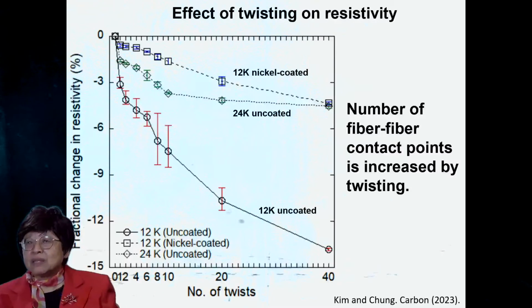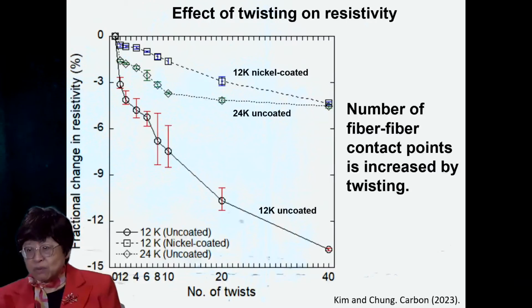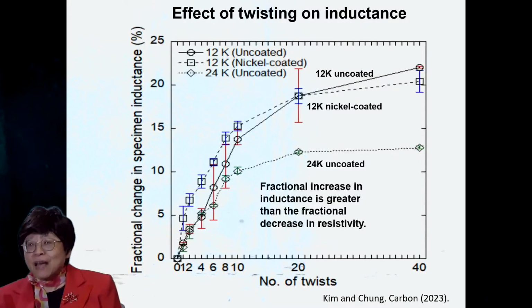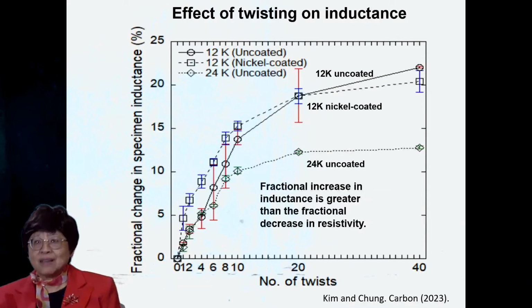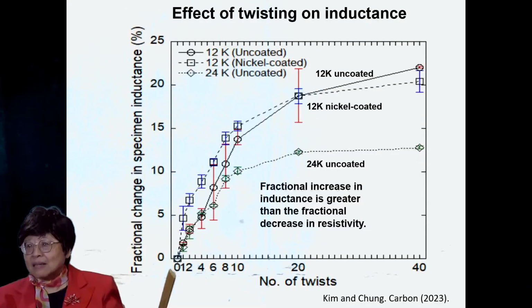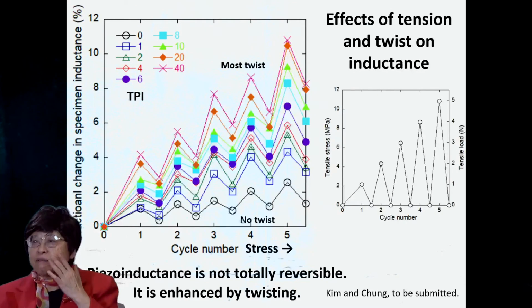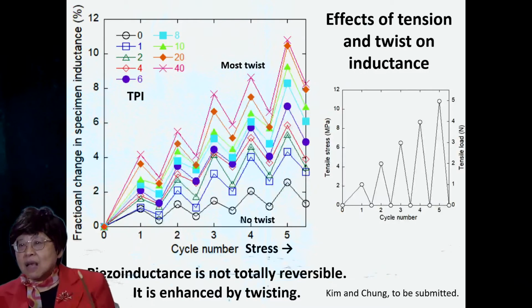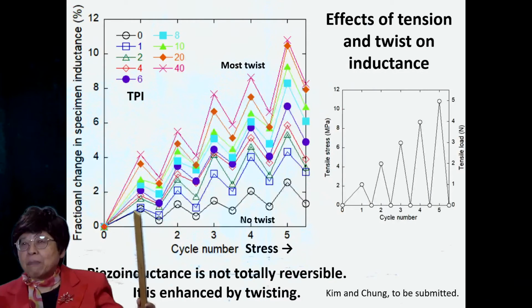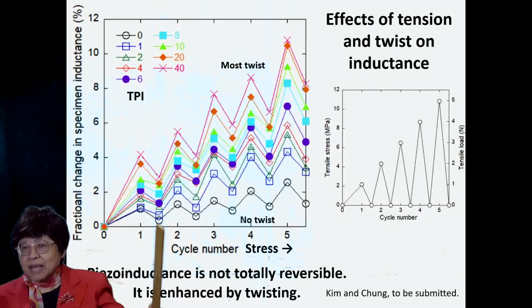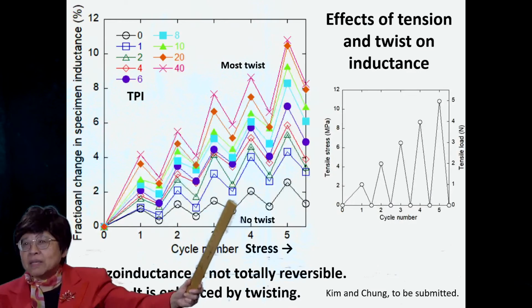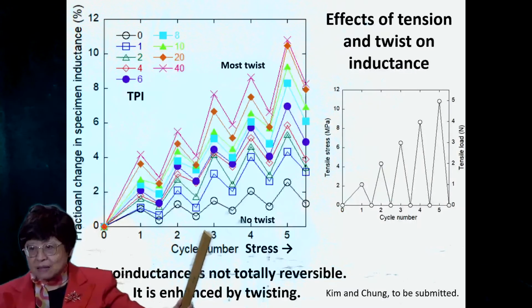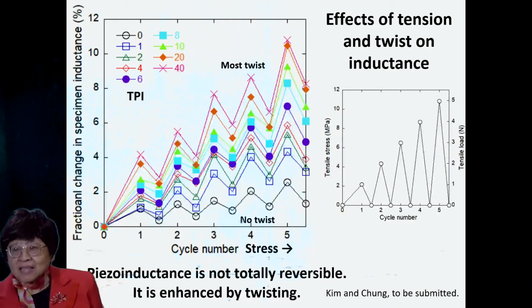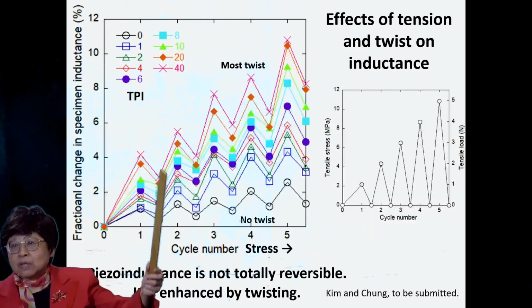And that decrease of the resistance with twisting is because the number of fiber-fiber contact points is increased by twisting. And this effect causes the inductance to increase. Having more fiber-fiber contact points would enhance the inductance, and that's exactly what we see. And this shows the effects of both tension and twist on the inductance, and the inductance increases upon stress application. This is tensile stress, and the more is the twisting, the more is this effect. So the piezo inductance is enhanced by the twisting, and is not totally reversible, as you can see.